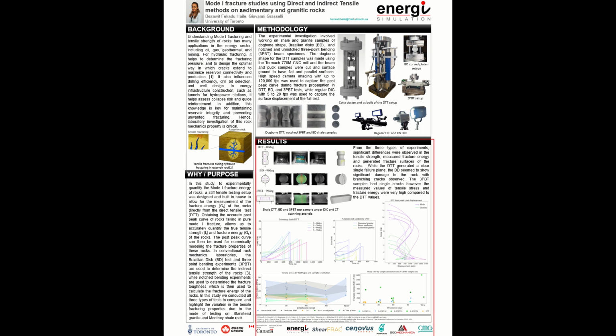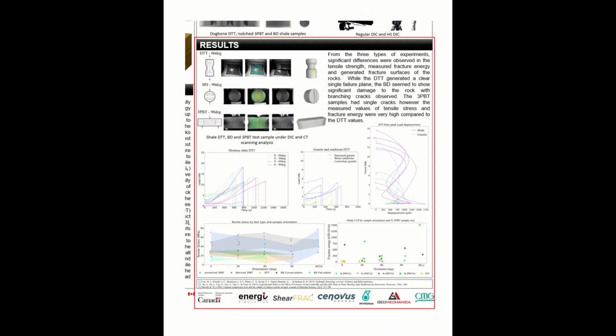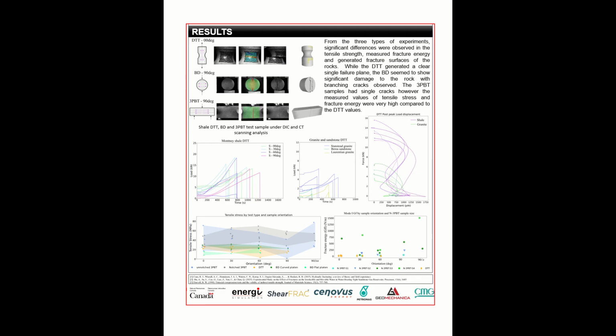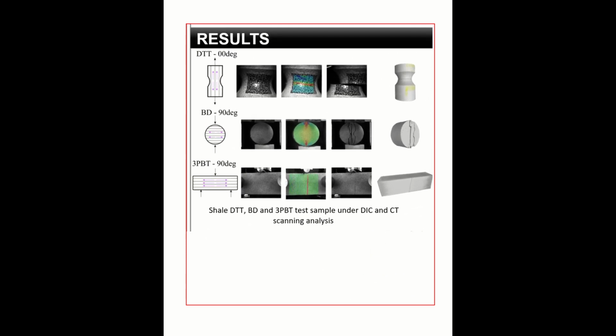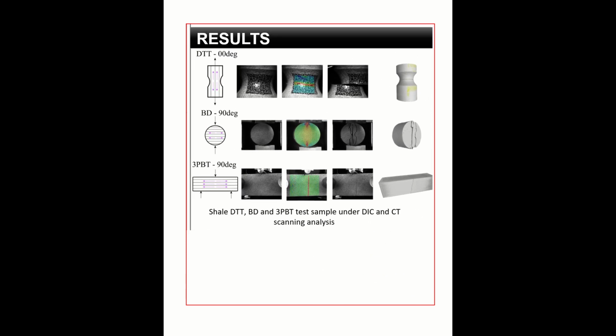The final results we have obtained so far are as follows. From the three types of experiments, significant differences were observed in the tensile strength, measured fracture energy, and generated fracture surface of the rocks. While the direct tensile and 3-point bending generated clear single fracture planes, the BD seemed to show significant damage to the rock with branching cracks observed, which can be attributed to the existence of a bimodal stress state, which is compression as well as tensile.